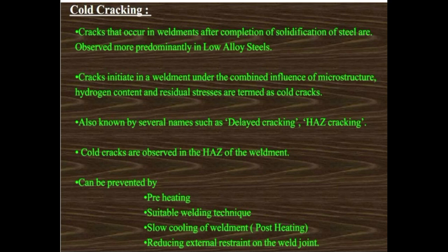Cold cracking occurs in the weld after completion of solidification — unlike hot cracking which occurs during solidification. These cracks are observed predominantly in low alloy steel. They are initiated in the weld under the combined influence of microstructure, hydrogen content, and residual stress. Cold cracking is also known as delayed cracking or HAZ cracking. It can be prevented by preheating, using a suitable welding technique, slow cooling, post heating, and reducing external restraint on the weld joint.